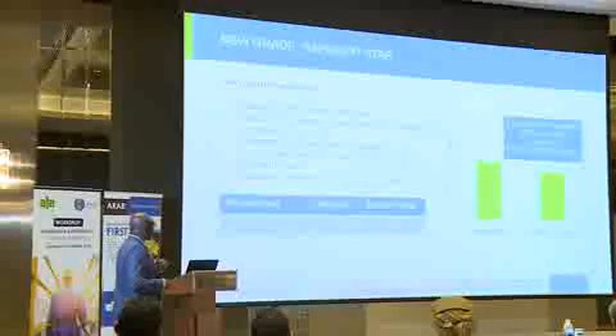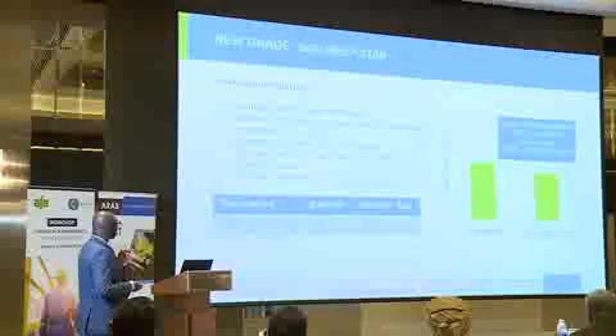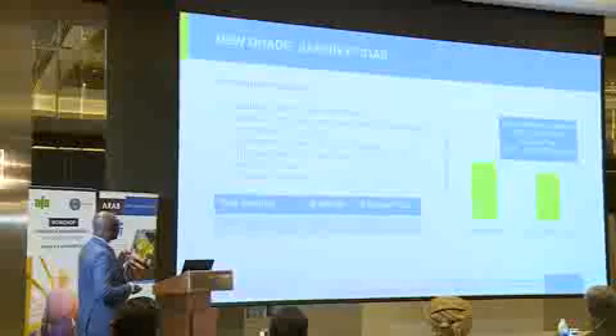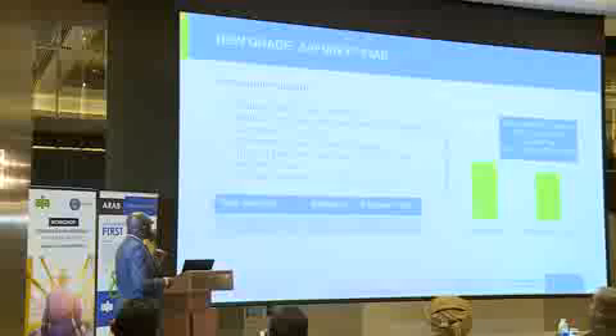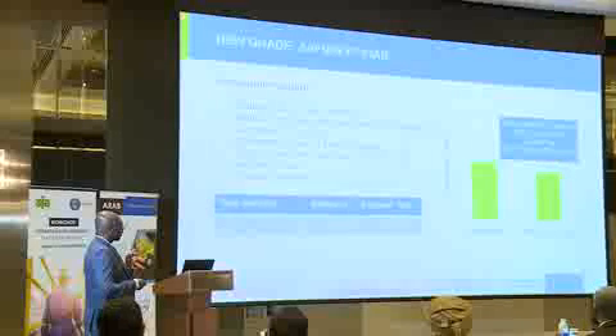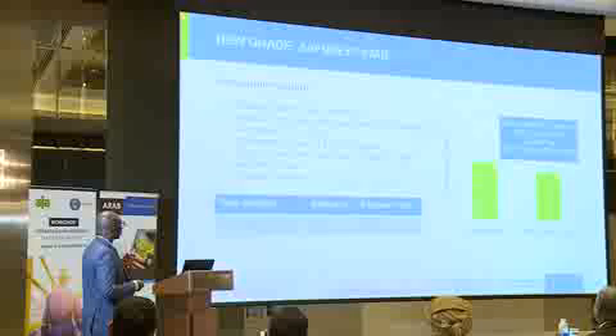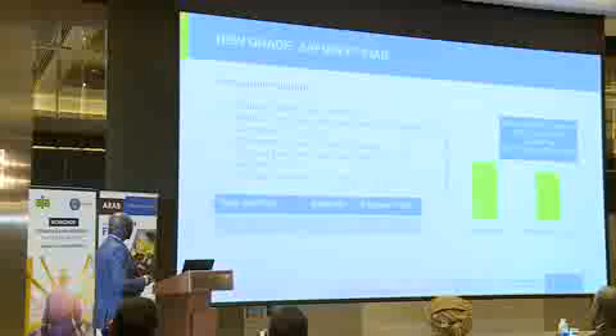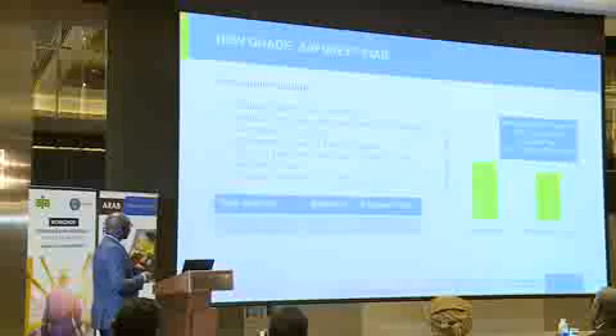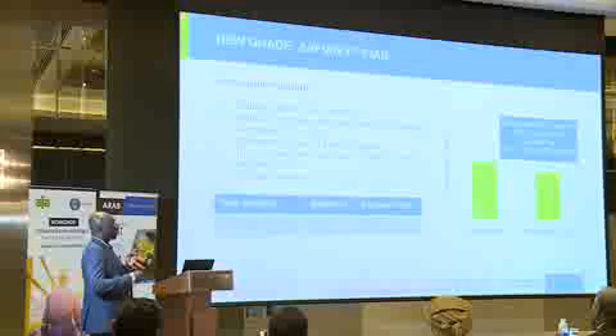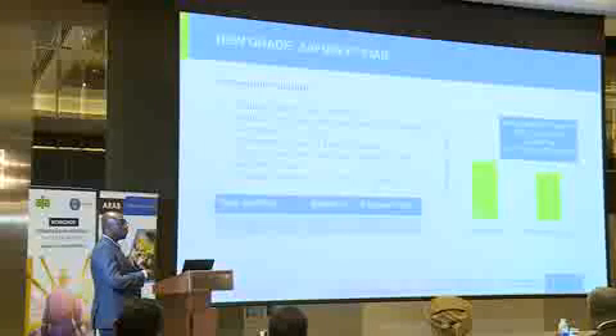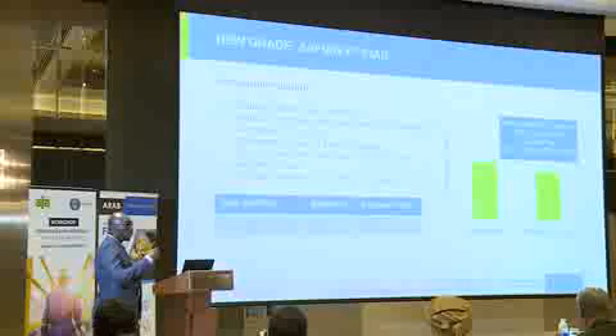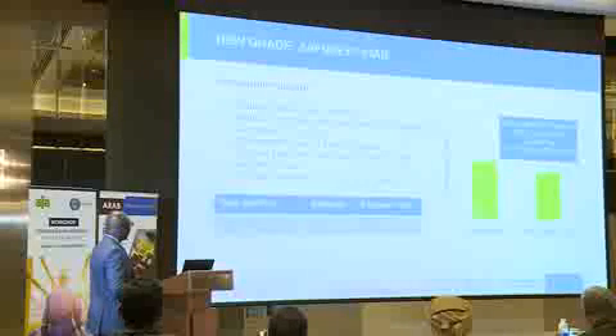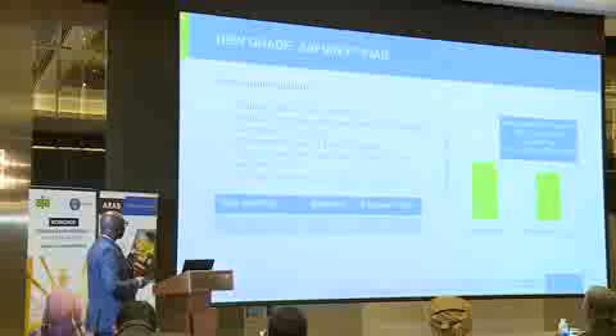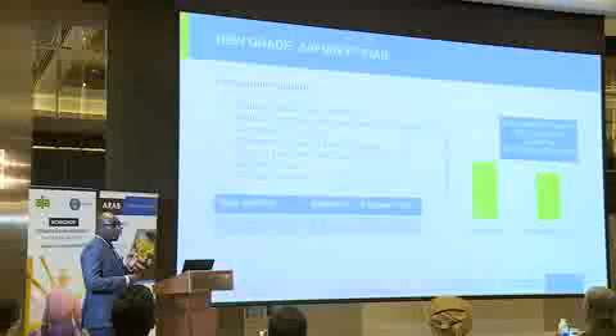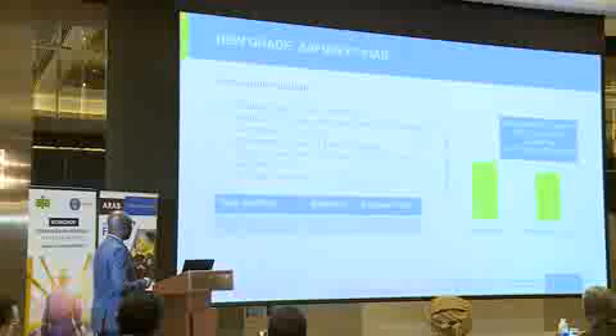When it comes to the corrosion resistance performance, comparing Saphorex to Saphorex Star, we have achieved at least 20% on the Saphorex, between 10 and 20%. This will increase the lifetime of the stripper. This value is just in terms of corrosion, but also because the mechanical strength is higher than Saphorex Infinity, it means you can also plug at a thinner wall thickness, which also gives you some extra lifetime. We have conducted field tests at a plant in Austria, and the results are also very excellent over there.